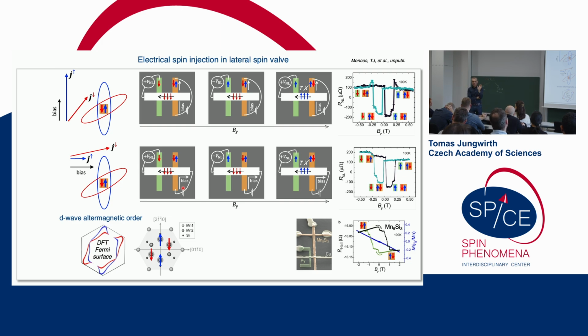I cannot exclude many things in this experiment, okay? So the only thing that is absolutely, for me, an undisputable experimental fact is that this is a compensated magnet in which I can do spin injection in this non-local spin valve geometry, okay? Also an experimental fact is that I can see it in both biasing geometries. That's already quite unconventional compared to normal ferromagnets. And also an experimental fact is that if I don't have a proper sidewall interface, I don't see it.